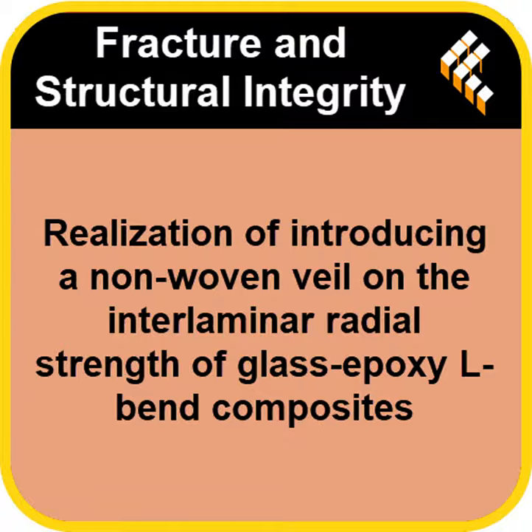So why the difference? Why can glass handle higher density? It comes down to flexibility, or deformability, as the engineers call it. Because glass fibers are less stiff, even when packed more densely in the veil, they remain more compliant. They can bend and move more easily with the resin. Exactly. They don't form that rigid barrier like the dense carbon did. This allows the epoxy matrix to flow around them better, create a better bond, and the veil itself can deform more to absorb energy as a crack tries to form. It distributes the stress better.